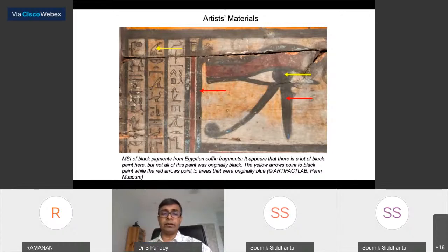Egyptian blue is one of the first synthetic pigments that were created about 3000 BC. And this is a double salt of calcium and copper silicate. Now, why does this darken? There are a number of theories, but one is that the copper breaks out of the pigment, converts into copper oxide, which is black in color. So this one, the blue pigment converting into a black pigment, was studied using multispectral imaging.